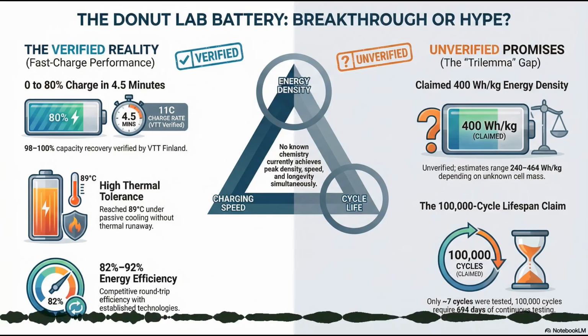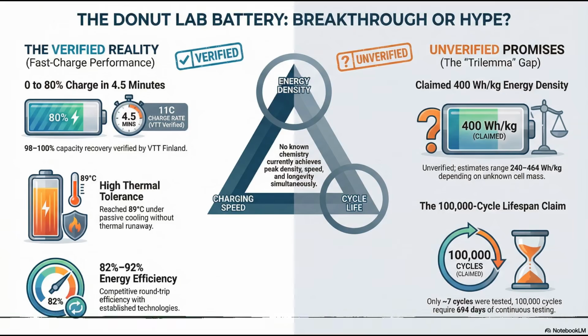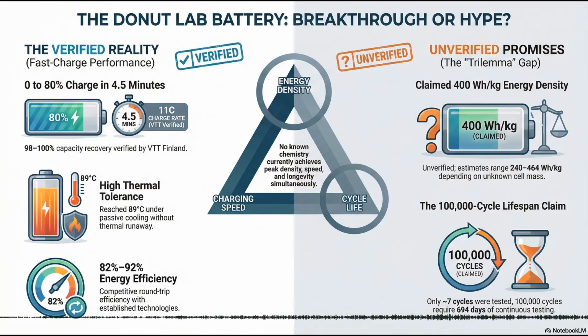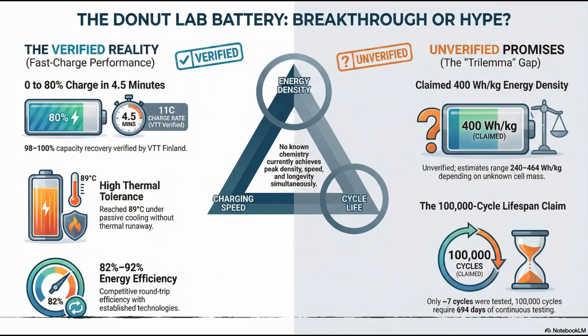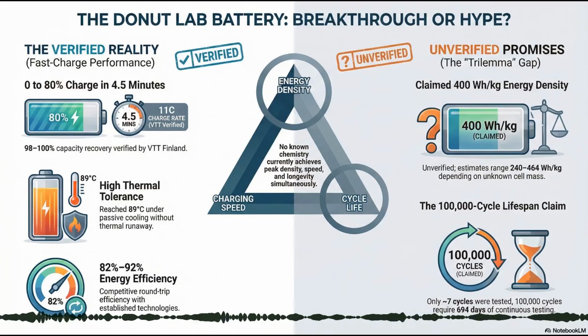So when you heat the material up... You provide that thermal energy. Exactly. The lattice vibrates, the hopping mechanism becomes much easier, and the ionic conductivity skyrockets. In many solid electrolytes, ionic conductivity doubles for every 20 or 30 degree increase in temperature. So by letting the cell get hot, Donut Lab wasn't just being lazy with their thermal management. They were strategically using the I²R heat to lower the internal resistance. That's my read on it. The heat wasn't a waste product to be managed. It was an active mechanism to enable the speed.